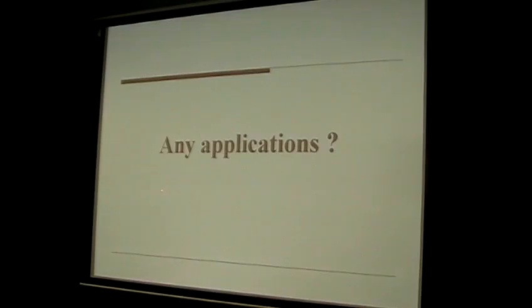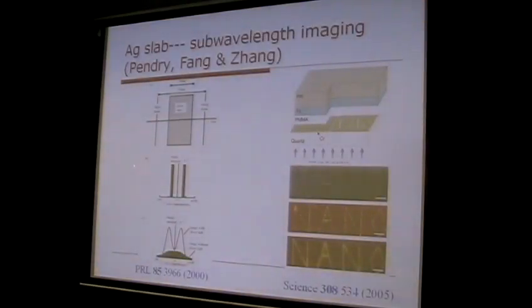Now the question is, do we have any applications? I already mentioned that in 2000, Pendry proposed that negative index material can behave like a perfect lens. And even if you do not have a negative index, if you have a negative epsilon, you also have a superlens. This idea was demonstrated by Professor Zhang Xiang's group in 2005 in a Science paper. They used a silver slab as a near-field superlens, and they found that it can enhance the resolution very dramatically.